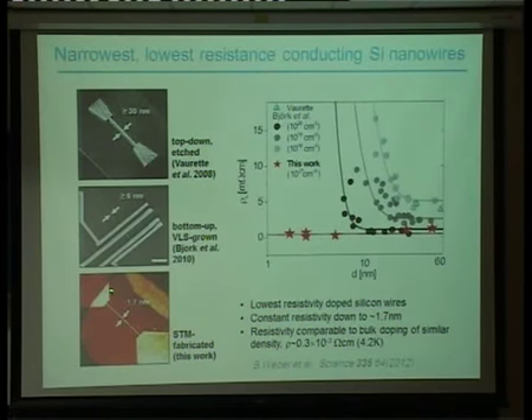And so try and understand why this is happening. The key difference with our devices is that we have this incredibly high doping density where the wave functions are essentially overlapping, so they're so close together that you form these extended states. But the other critical thing is these devices are then a long way from the surfaces, so they're encapsulated with silicon. So as a consequence, they're not interacting with surface states. They have a dielectric, which is essentially a long way away. The silicon oxide is a long way away.